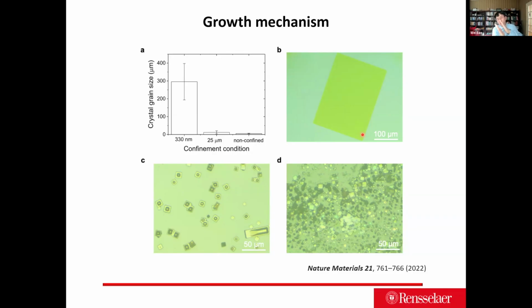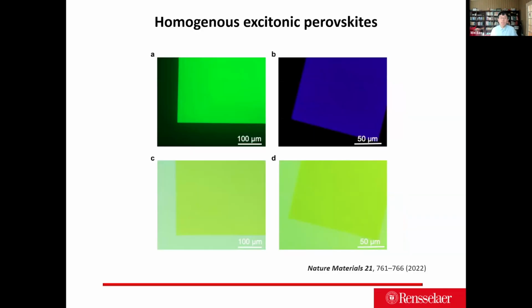In this way, all the single crystals grow and fill in all the nano cavities everywhere, and the crystal shape is controlled by the nano cavity, not by the growth dynamics. So those materials really generate a really homogeneous excitonic emission, as demonstrated by our Nature Materials paper. Here is the cesium lead bromide. Here is the cesium lead chloride. You can see really uniform, homogeneous photoluminescence.